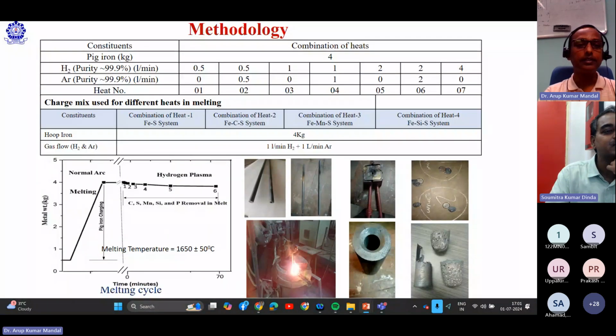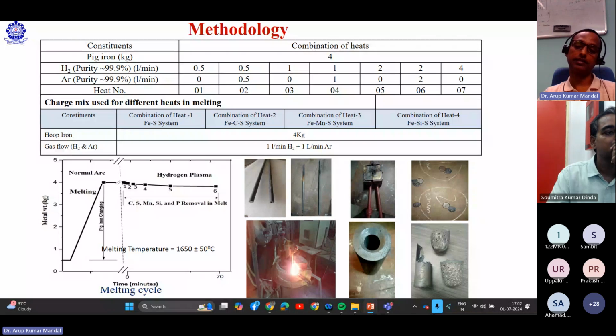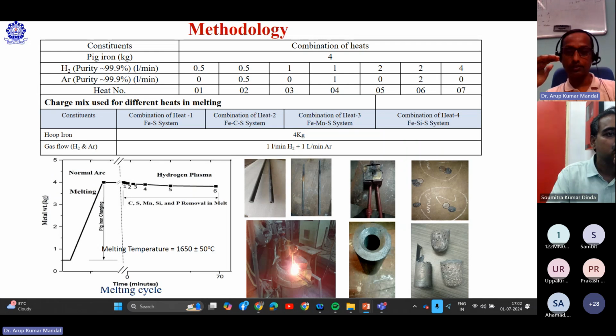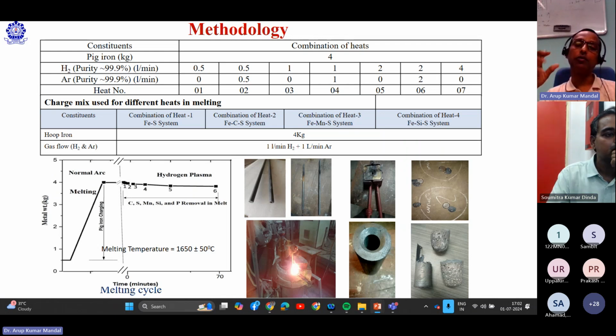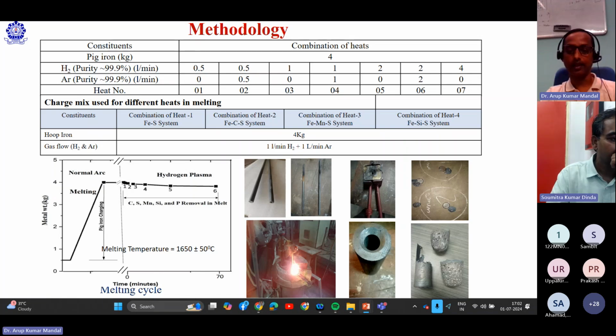You can see here our pig iron is 4 kg because our capacity is 4 kg. Therefore, the pig iron content we have taken is 4 kg. But if we go for the smelting reduction route, where slag will be generated, then capacity enhancement is required, like crucible size enhancement, because some free board area is required so that we can accommodate the viscous slag. In that condition, we generally take 2 kg of liquid metal and keep the remaining portion as free board area for accommodating the extra viscous slag.